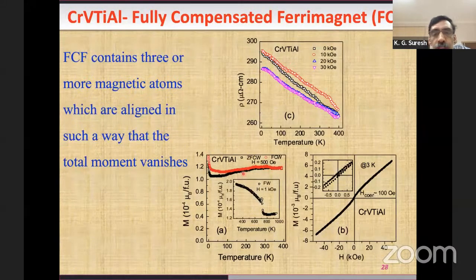Again, we were doing some work on this system. What happened is that we see this rho versus T behavior, which is not the metallic thing. Then, of course, we thought that it must be something corresponding to a spin gapless kind of thing. Then we measured the magnetization. We found that the magnetization is very low, 10 to the power of -4 is here. So it's almost a very low moment. But at the same time, it has got a little bit of hysteresis. So it is not clearly an antiferromagnet. Therefore, we thought, okay, something is happening in the system. We took a lot of time to understand.